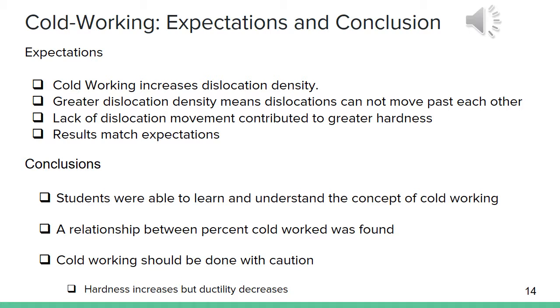Finally, the expectations and conclusions of this lab will be discussed. It was expected that cold working would increase dislocation density. Greater dislocation density means that dislocations cannot move past each other. The lack of dislocation movement contributed to greater hardness in brass cartridge samples. The results of our experiment match these expectations, with hardness increasing as cold work increases.